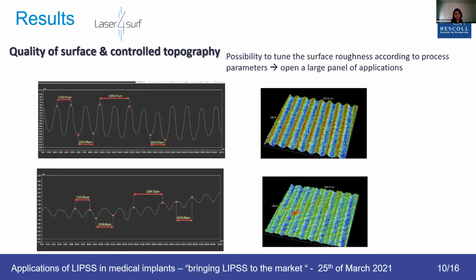So briefly, I wanted to show you key results we obtained during the project. First of all, we can see that we have a very good quality of the surface. This is a 3D mapping of the implant surface. We have very well organized and very repeatable periods on the surface. And what is very interesting is that according to the process parameters, we can play on the size of the features, but also on the depth of the features. So depending on the application, we can very finely tune the surface roughness and the surface isotropy according to the need and to what we are expecting from the implants. So this opens a large panel of applications.